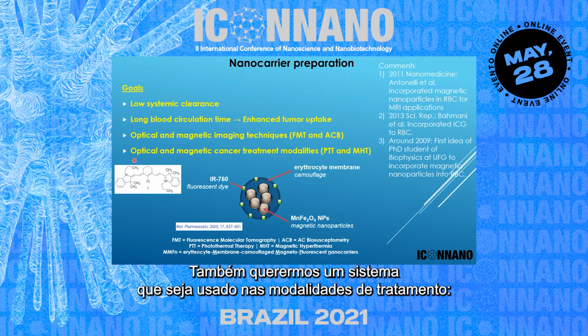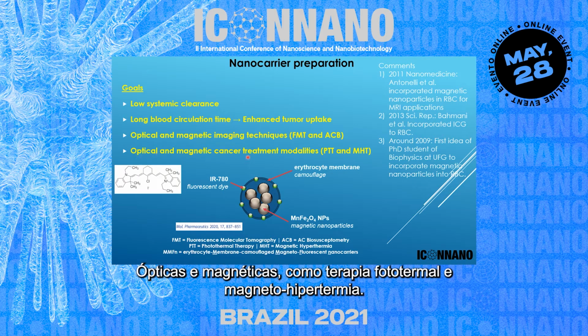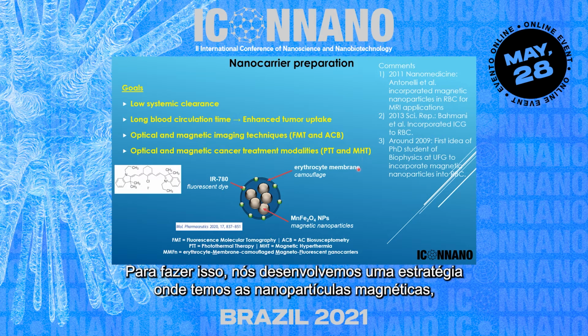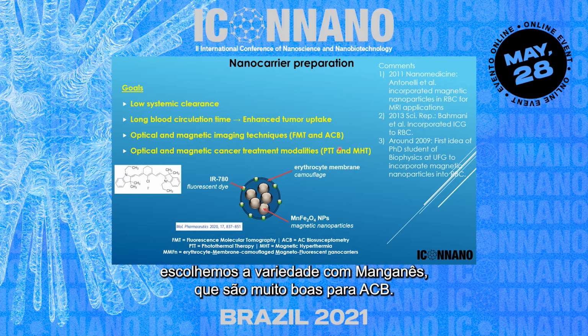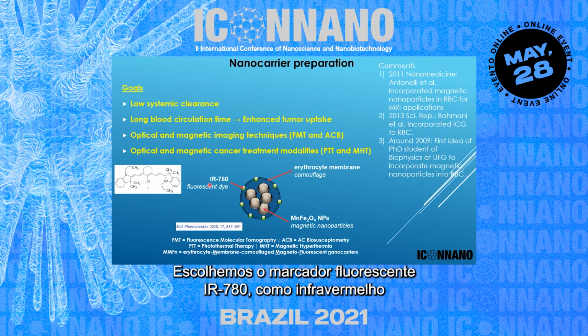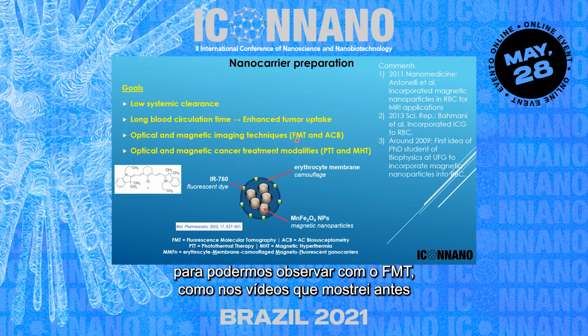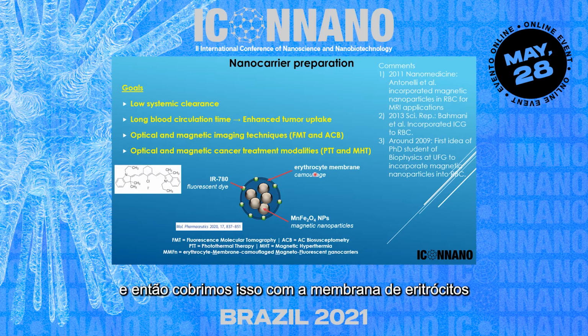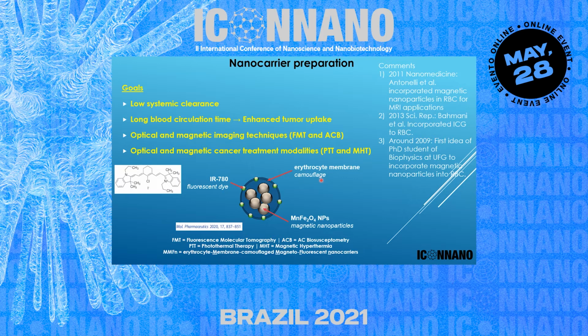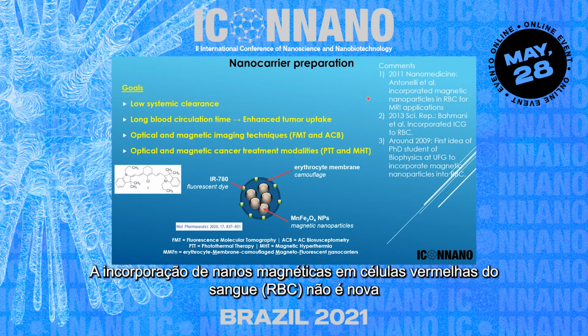And we also wanted a system that could be used for optical and magnetic treatment modalities for nanomedicine, such as photothermotherapy and magnetic hyperthermia. So to do that, we developed a strategy where we have the magnetic nanoparticles, for which we chose manganese ferrite, which is very good for ACB. We chose IR 780 as the near-infrared molecule, which we can observe by FMT, as in the movies that I showed you before. And we then coated it with the red blood cell membrane. I should comment here that the incorporation of magnetic nanoparticles in red blood cells is not new.